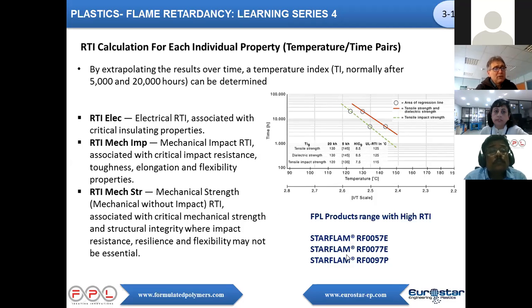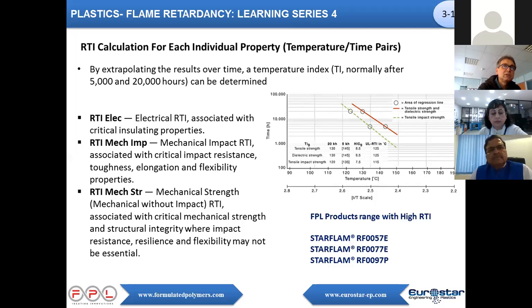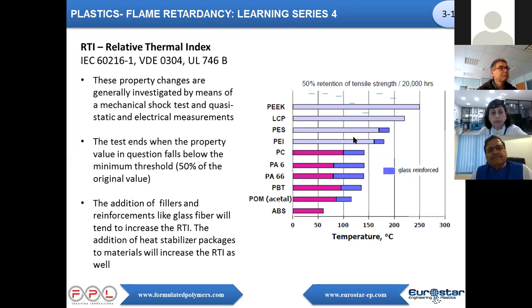So FPL and Eurostar are really a very nice range of products, and it's a very nice asset, because you have to know that this test lasts for about 18 months, and it's really a big investment. A yellow card with a full RTI costs $100,000. And we are in this market for so many years that we have very documented material, and we have even material that has RTI above 150 degrees C. And this is quite exceptional, let's say.